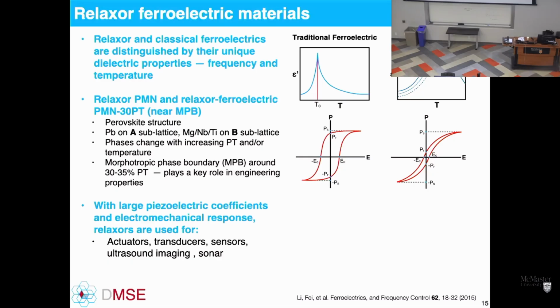And the relaxor we're going to look at today is PMN-30PT. This is lead magnesium niobate lead titanate, a 30% lead titanate solid solution. It's a simple perovskite structure, lead on the A sublattice, magnesium, niobium, titanium on the B sublattice, and you get phase changes with increasing PT or temperature. And you also get a morphotropic phase boundary at 30%-ish PT.